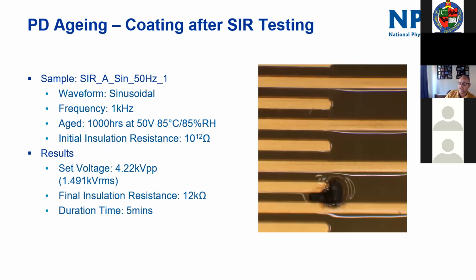So this is below the dielectric withstanding voltage. It's well below the dielectric breakdown voltage for this coating. Literally, 5 minutes surprised us, I will admit. We were thinking it could be some hours before it failed, but it went from about 10 to the 12 ohms down to about 12 kilo ohms within 5 minutes of testing it at less than 1,500 volts RMS.